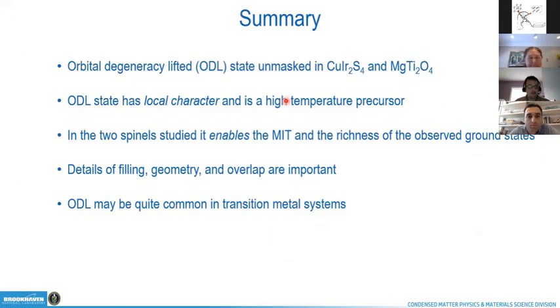So this is my summary. Orbital degeneracy lifted state is discovered in iridium and titanium spinels displaying a metal insulator transition. Presumably this state has a local character, as shown, and it's a high temperature precursor to what happens at low temperature. In the 2 spinels studied, this state enables the metal insulator transition and the richness of the observed ground states. The details of filling, geometry, and overlap are important for this state. And this ODL state might actually be quite common in transition metal systems.